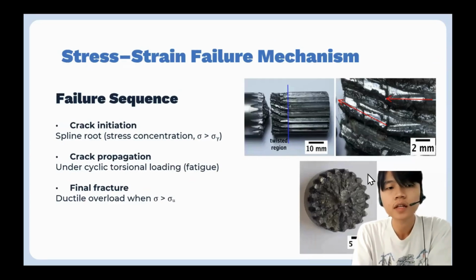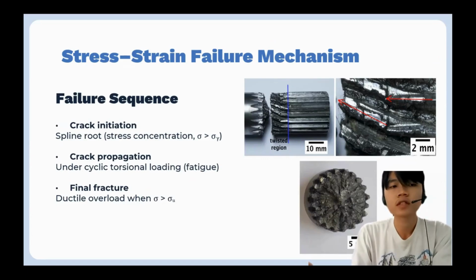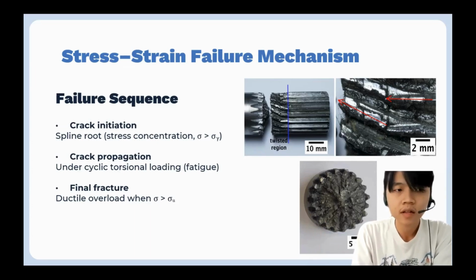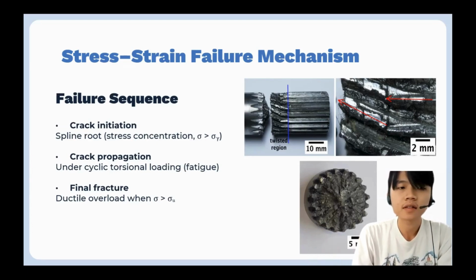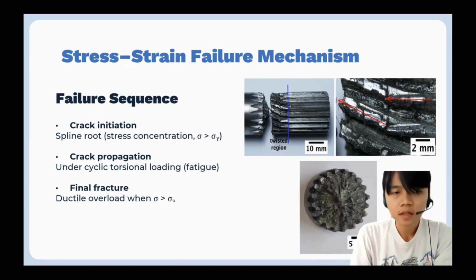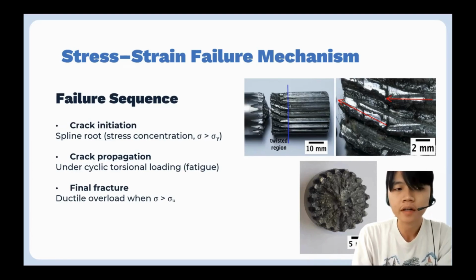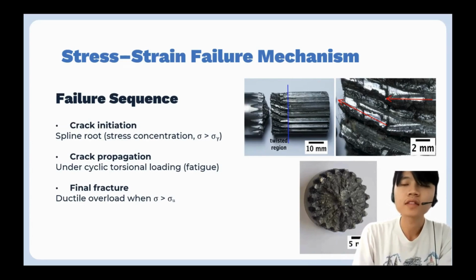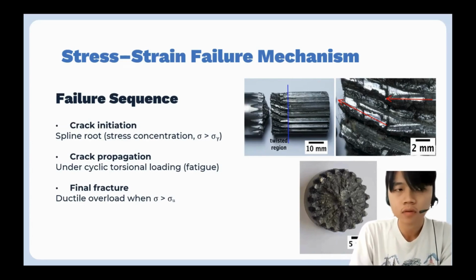Okay, now the failure of the half shaft can be broken down into three stages. First, the cracks initiated at the spline roots, where the stress concentration is at the highest point, and in this case the stresses exceeded the yield strength of the material. Next, under repeated torsional loading, these cracks slowly propagated, and this is a classic fatigue process. Finally, once enough of the shaft's cross-section was consumed by the cracks, the remaining ligament could not sustain the applied torque. At that point, the stresses exceeded the ultimate tensile strength, and this caused the rapid overload fracture. This is confirmed by the twisted splines seen on the fracture surface.